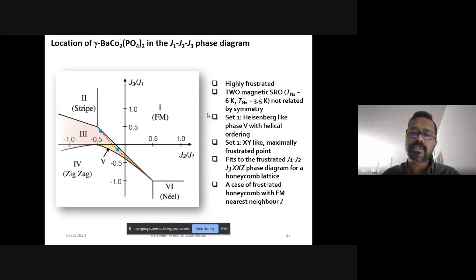And the J values that we get are slightly confusing, because one of them is Heisenberg-like and the other one is XY-like, but they conform to these blue points, which are actually highly frustrated regions straddling the boundary between two different phases. So this is the understanding that we have.